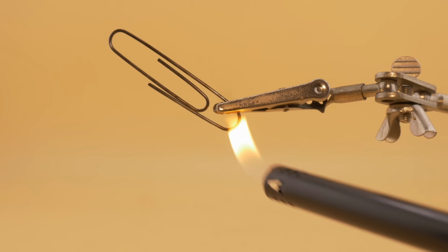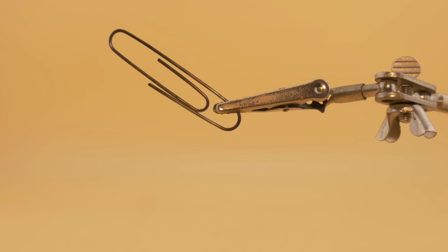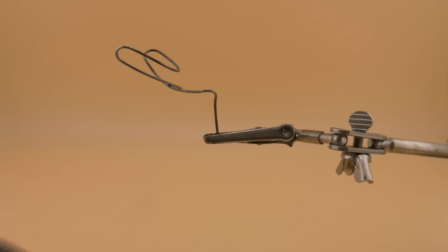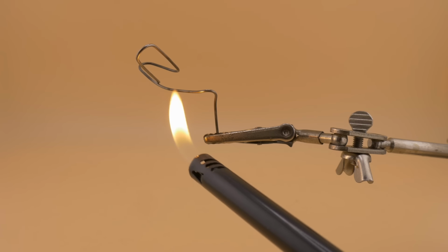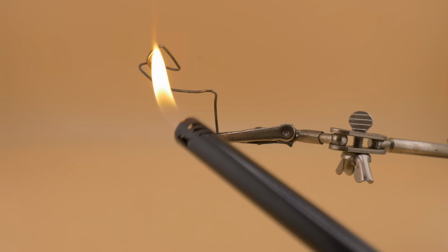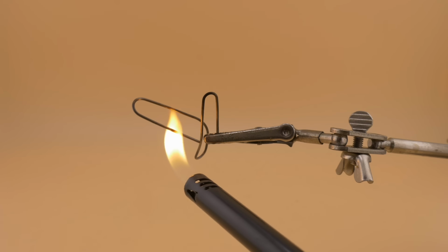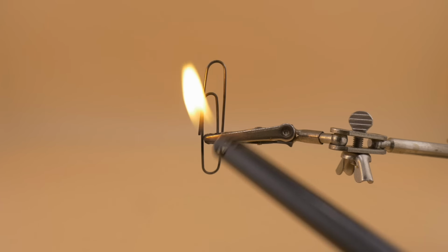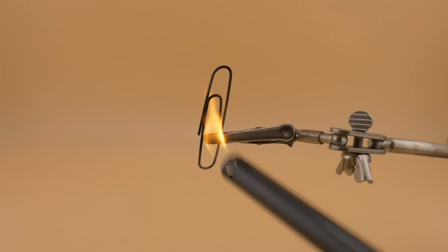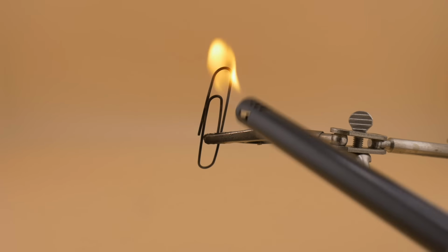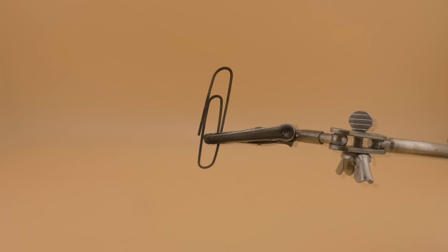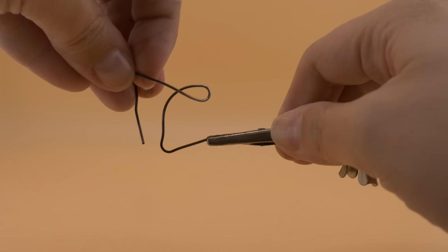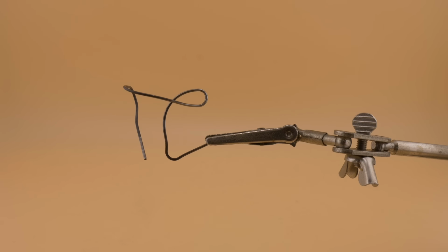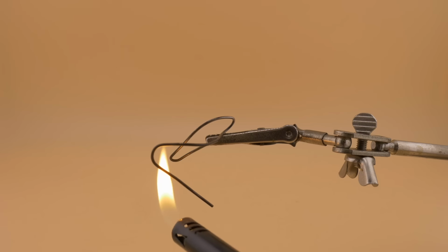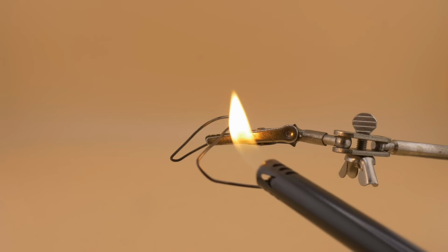Shape memory effect means that you can deform an object made of nitinol, bend and twist it, and as long as it is below a certain temperature, it stays that way. But heat it up above its transformation temperature, and it will spring back to its original shape, as if by magic. Superelasticity means that at warmer temperatures you can bend it a lot and it will snap back immediately upon release, like an extremely rubbery metal, as long as you don't exceed a certain strain.